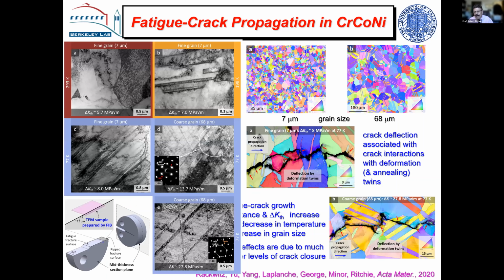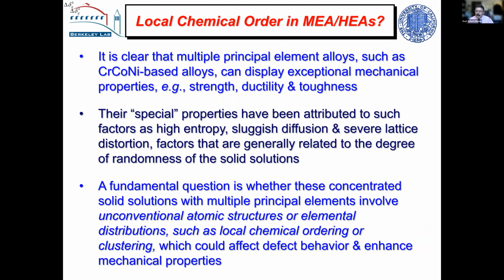But the last thing I want to talk about is a little different. These are multiple principal element alloys, and these FCC structures show, I think, the most exceptional damage tolerance that we've seen in any material. And these special properties associated with these alloys, people talk about high entropy, of course, sluggish diffusion, severe lattice distortion, because you basically have different size atoms in there, but they generally refer to the randomness of the solid solutions. But a question we asked a couple of years ago is, are they random? Are there any unconventional atomic structures or elemental distributions, such as clustering or local chemical ordering, that might affect or enhance these properties?